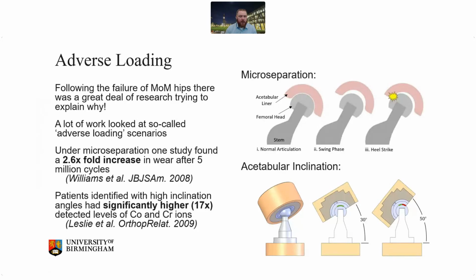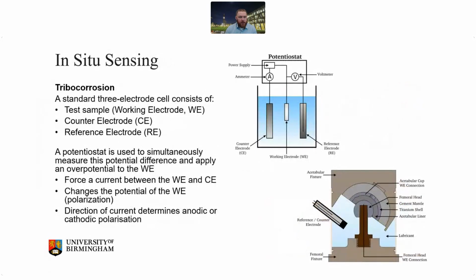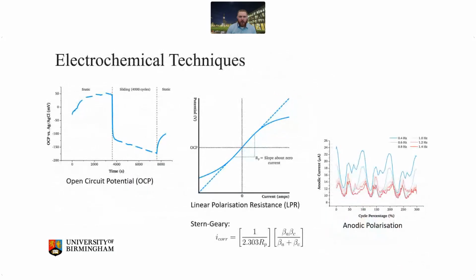So one of the branches that we've looked at is instrumenting simulators with a 3-electrode electrochemical cell. And this allows you, during articulation, to measure and extract information around the corrosion of those devices. So this was the bulk of the focus of my PhD, looking at metal-on-metal bearings. We use a potentiostat, which is essentially a fancy voltmeter and ammeter, to connect to the metallic surfaces, and then as sliding happens, you depassivate that metallic alloy, the oxide film interrupts it, and corrosion happens. You can draw direct measures for the corrosion that's taking place.